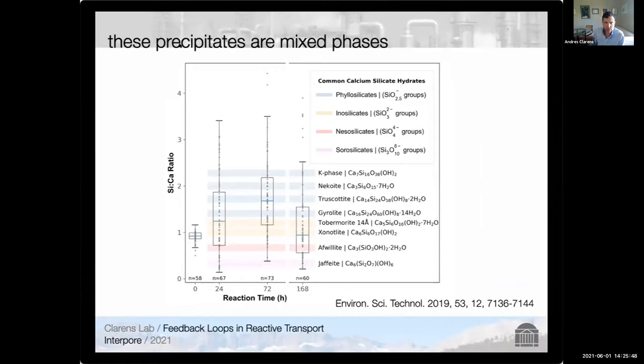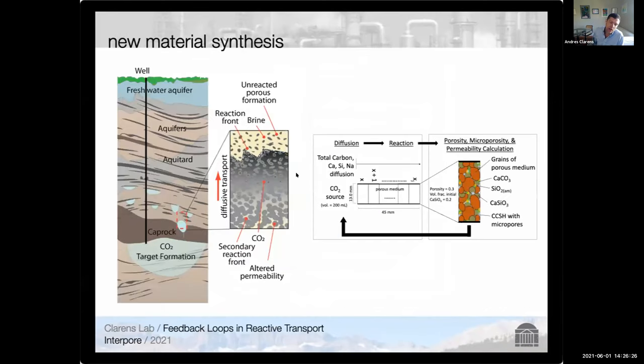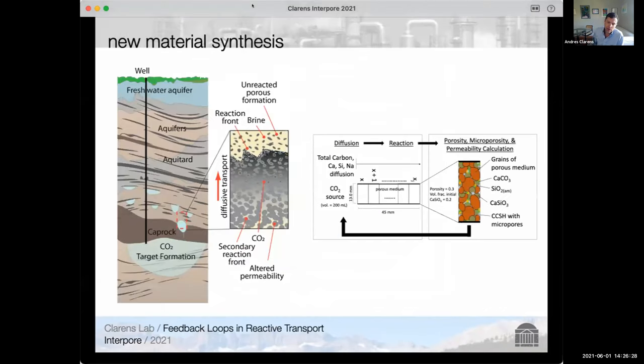Some of these results were published at the end of 2019. As for what these phases are precisely — even starting with idealized calcium silicate minerals, we are generating a variety of different phases. Tobermorite might be one idealized calcium silicate hydrate, but we're seeing other phases as well, some of which incorporate CO2 and some of which don't. Understanding this precise mechanism is very much a focus of our group right now.